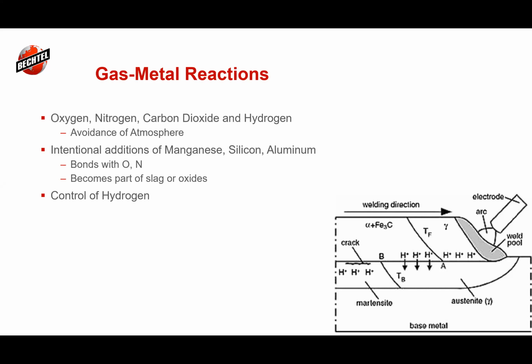because what happens is this diagram talks about the hydrogen actually has a tendency to go out into the fusion line, into the heat affected zone. And if we've ever experienced some of the hydrogen cracking, a lot of the times we can see what is called underbead cracking, where it cracks right at the toe of the weld. It's a susceptible area. The hydrogen has a tendency of accumulating there. And then that's also where we typically have stress risers or increases of stress concentrations.